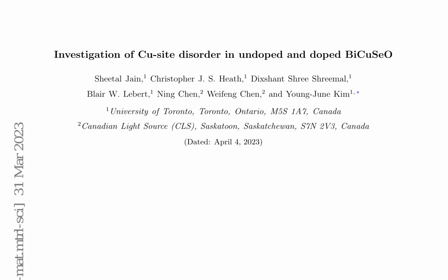In both subfigures, A and B, all XRD peaks for the doped samples align with those obtained for the undoped sample, indicating phase purity. However, a minor impurity peak attributed to unreacted bismuth-3 oxide, present at less than 0.5%, is observed near 27 degrees for some samples. This suggests that the synthesis process has been successful in producing high-quality materials with minimal contamination. This phase purity analysis is essential for ensuring the reliability of subsequent physical property measurements and device fabrications.